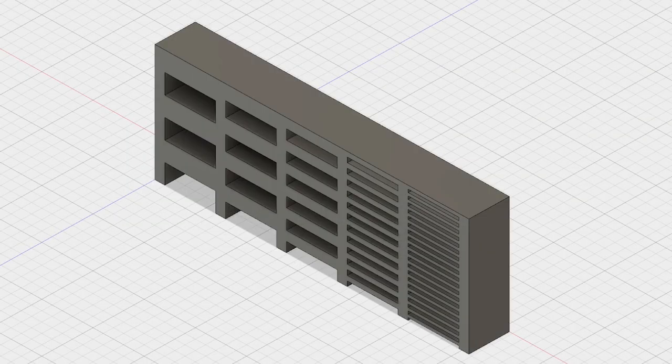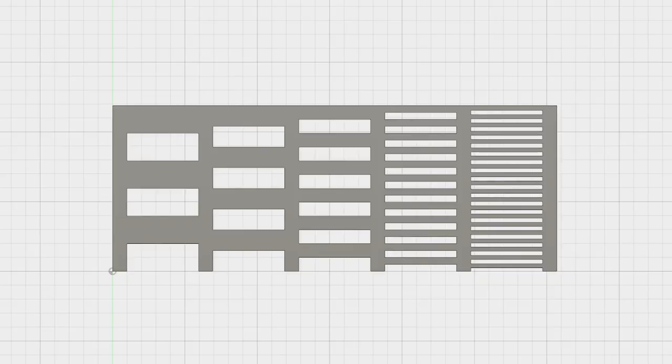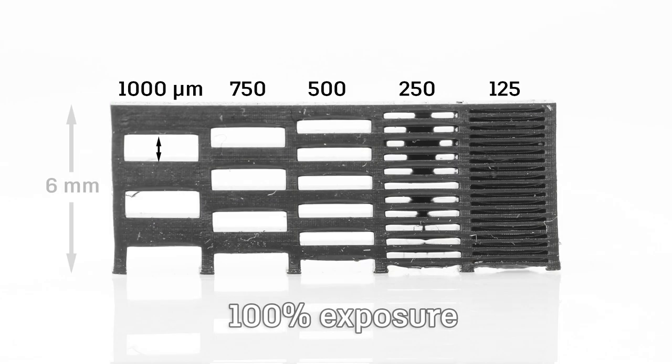For models with small negative features, too much light energy can be a problem. If we dial in the exposure, the 500 micron and larger gaps are clearly resolved.